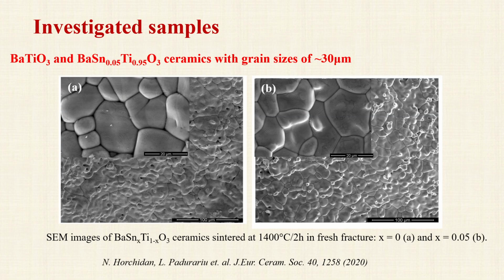The two investigated systems for comparison with the theory results are dense ceramics of pure barium titanate and doped barium titanate with 5% tin substitution on the titanium position. The samples were prepared by solid-state reaction. The scanning electron microscopy investigations demonstrated that the samples have good densities and high grain size, thus not being affected by the porosity or grain size effects.